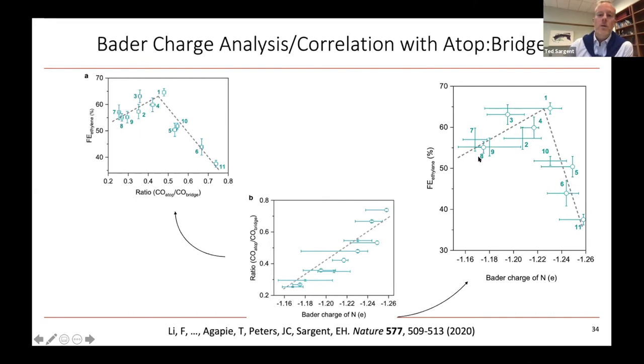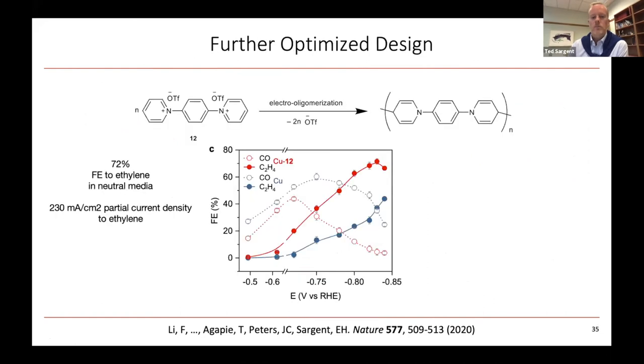And then you'll see, for those of you who work in this field, very much a volcano plot, but an experimental volcano plot, where both by tuning the experimentally observed ratio of atop to bridge and correspondingly the Bader charge computed, we were able to achieve an optimal Faradaic efficiency, the vertical axis, FE to ethylene, and get it to about 72%, whereas previous work in neutral electrolyte was limited to about 60% in the absence of this strategy.